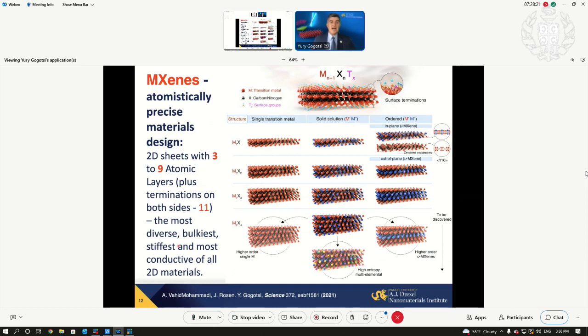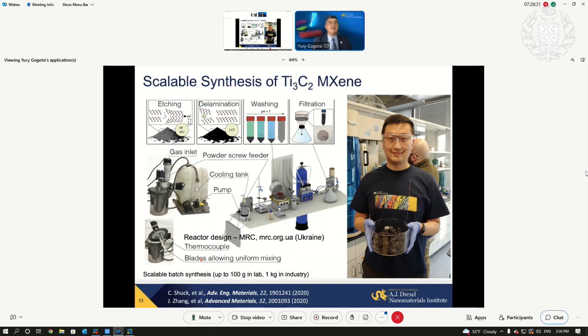And they actually are not only the most diverse, but they provide extreme mechanical properties and metallic conductivity, greatly complementing chalcogenides, oxides, other semiconducting and dielectric materials. Recall that graphene, praised for its conductivity, is a zero band gap semiconductor. Many MXenes are true metals with a high density of states at the Fermi level, high concentration of carriers here. Moreover, unlike many exotic materials, they can be made in large quantities.